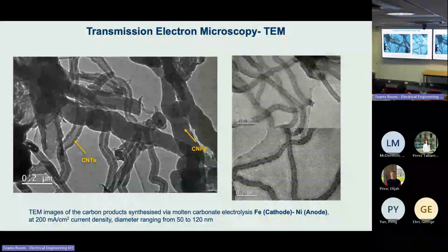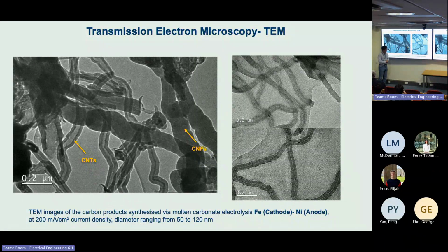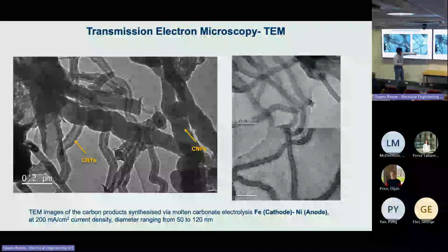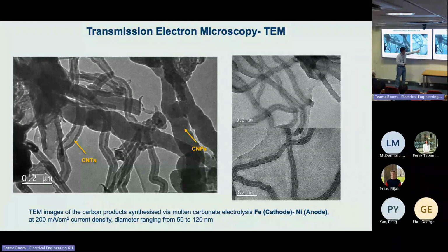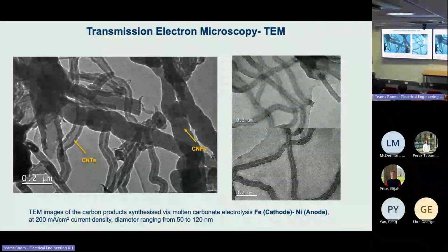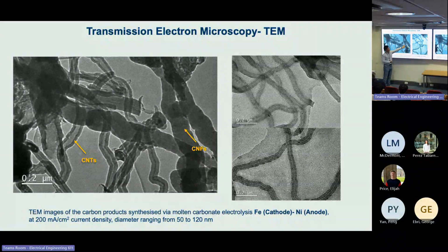So these are the TEM images of our products synthesized by the best electrode configuration, using iron electrode as a cathode and nickel wire as the anode. You can see we also generated carbon nanotubes because it has a central hollow structure, as the TEM images suggest. We also have some solid ones with no hollow structure, so that's carbon nanofiber instead of carbon nanotubes.